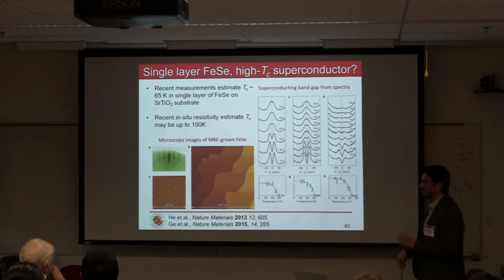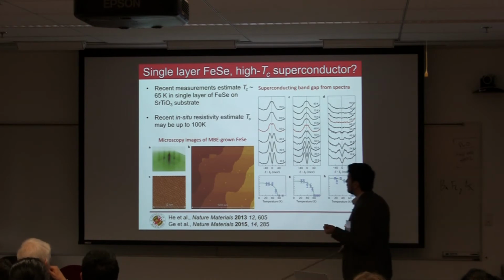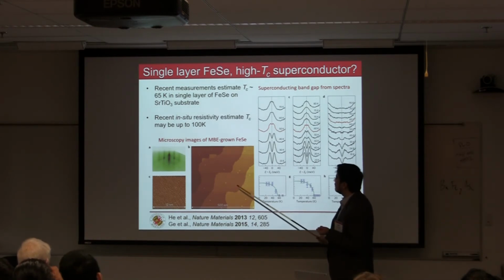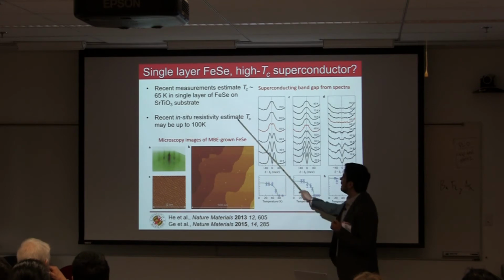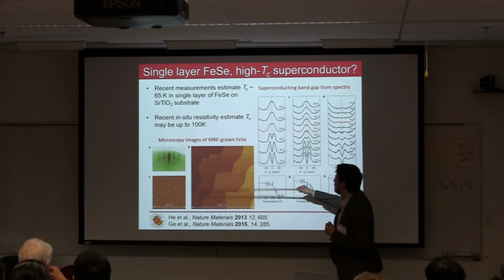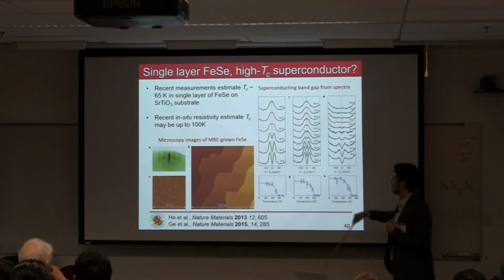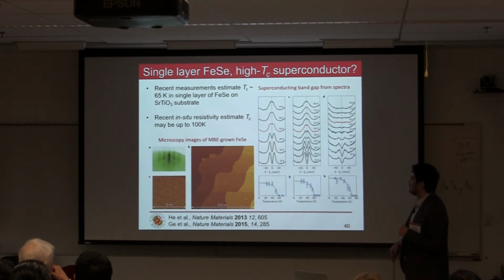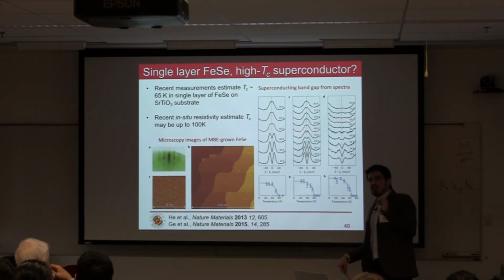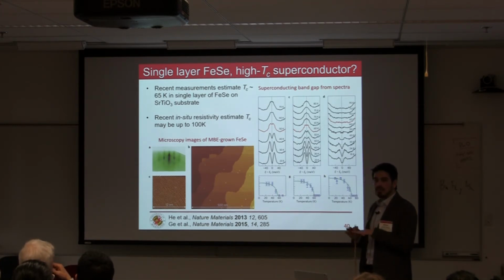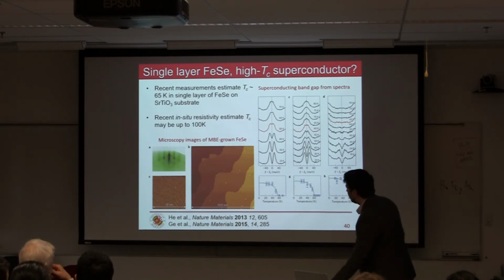Here's an example of something very exciting that can happen in iron selenide. If it's grown by MBE as a single layer or very thin films, you can actually raise the TC up to 65 Kelvin on strontium titanate. There was one report I read about 100 Kelvin, but I don't know exactly where the consensus is now. But you can see that what's very important here is that square lattice of the iron, and how possibly it could be changed as a function of the strain or something like that on the substrate.